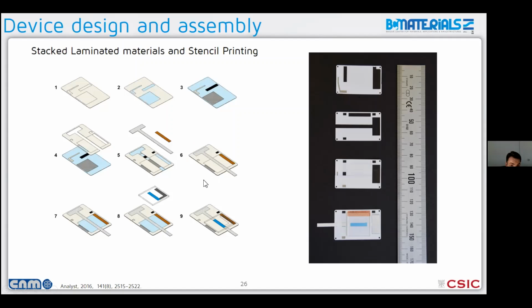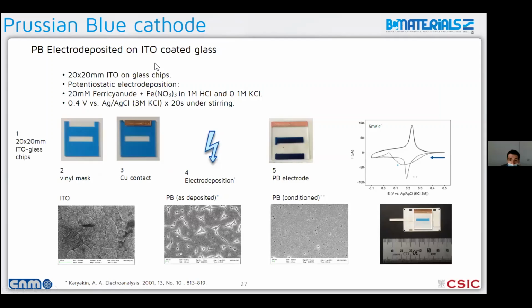Then we used a lateral flow membrane to facilitate the exchange of solution in the system and be able to reuse it. And then we used an electrodeposited Prussian blue cathode on a piece of glass with an ITO coating. So what we did was actually we used a vinyl mask cut in a cutter plotter to define the area where we wanted to grow the Prussian blue. We ran some electrodeposition using a recipe described by Karyakin, which works really well.